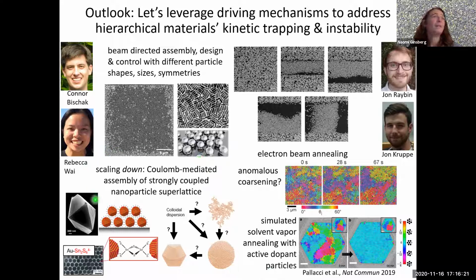And then finally, we're also interested not so much in scaling up, but scaling down. So we have ongoing work in my lab looking at Coulomb-mediated assembly of strongly coupled nanoparticle superlattices, where these nanoparticles are 2 orders of magnitude smaller than the ones I was just talking about. And these are really cool systems by virtue of having very strong coupling, which can be challenging to orchestrate in these materials. You can make macroscopic superstructures like these, and we've been busily trying to explain the complex mechanisms associated with the formation of these sorts of structures, why we can make them when we have, say, metallic particles, but not so much yet with dielectric ones, something hopefully we can change by manipulating, perturbing, and controlling.